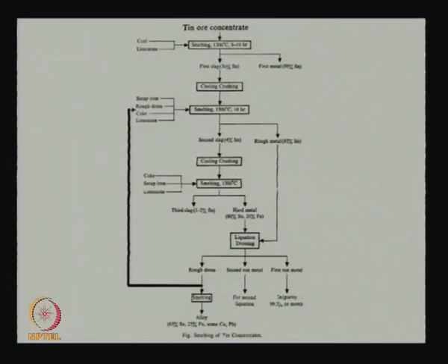So, we go through a third step, again add coke, limestone, scrap iron. In the third step, what is produced is only 80% tin and 20% iron, because you have added iron to dissolve tin. We will get a third slag. This slag now can be discarded, because it is only 1 to 2% tin. We can let that go.